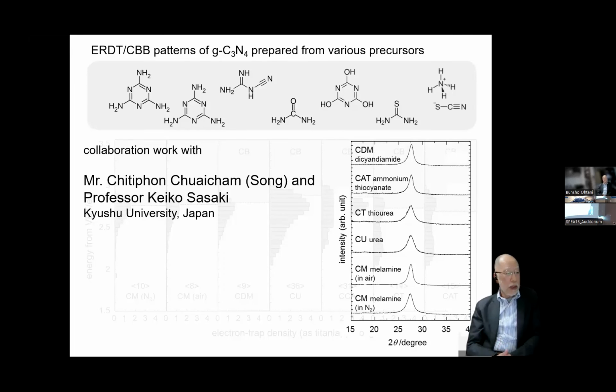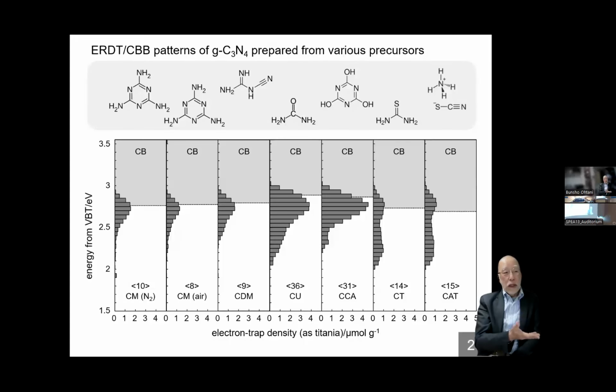limited to metal oxide, carbon nitride that can be used for photocatalyst can be measured by using RDB-PAS to give an ERDT pattern. So this is the collaboration work with Professor Sasaki, previously at Kyushu University. Now she is working at Waseda University. They prepared samples of C3N4 from different precursors containing heteroatoms. But the product is almost the same if the XRD pattern is observed. So almost the same XRD patterns. That means the bulk structure of those samples is almost the same, even if a different type of precursor was used. But the ERDT pattern is completely different.